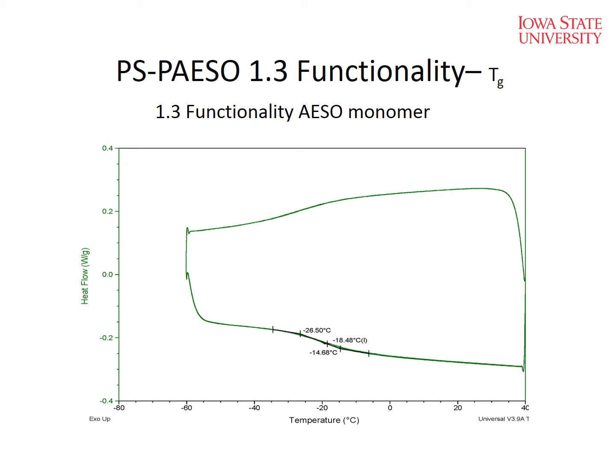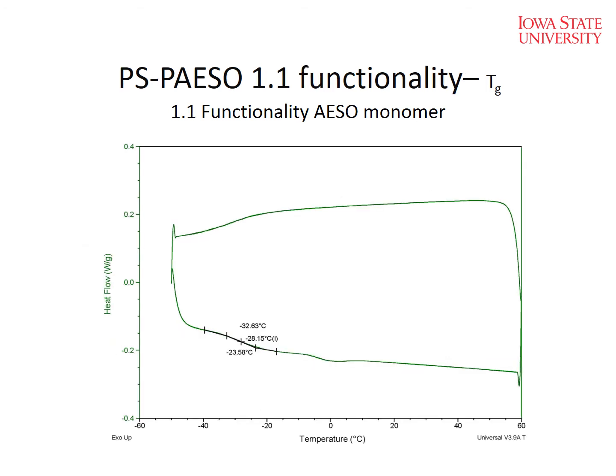And so when you look at the degree of acylation, if you will, okay? And this is just a DSC looking at the glass transition temperature, okay? And so what we're seeing is glass transition around minus 26 centigrade off of this particular monomer that we put into then our polystyrene polymer. PS-PAESO, polyacrylated epoxidized soybean oil. And then we can change that functionality down lower to 1.1. And we can drop the glass transition temperature down lower.